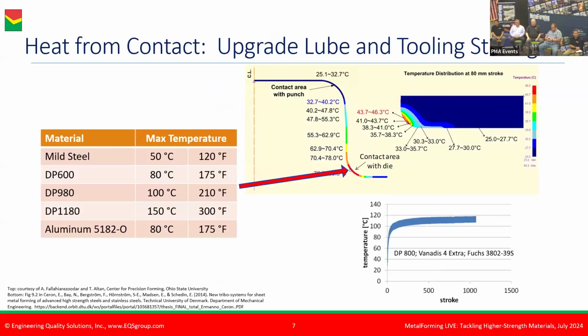As an example, you can see that this was based on a simulation, but verified with actual temperature measurements, again, for room temperature stamping. The friction from the contact of sheet metal with the punch and die material, for mild steel, is going to heat up the sheet steel to 120 degrees Fahrenheit. Our lubricants that we are using are designed for that. But if we swap in higher and higher strength steels, you see that we're not at 120 degrees, we're up to potentially 300 degrees Fahrenheit. Now, depending on your strength, up to 300 degrees Fahrenheit.